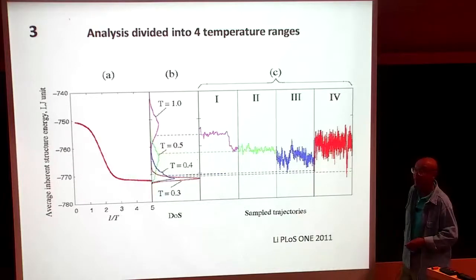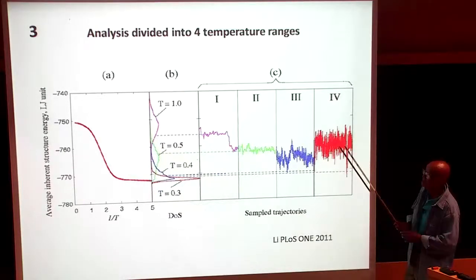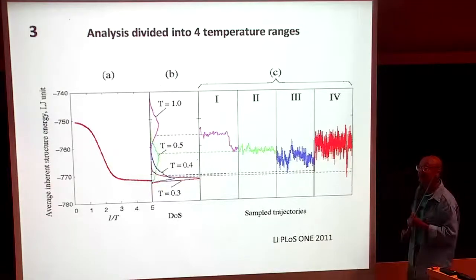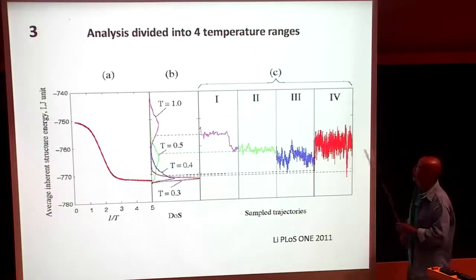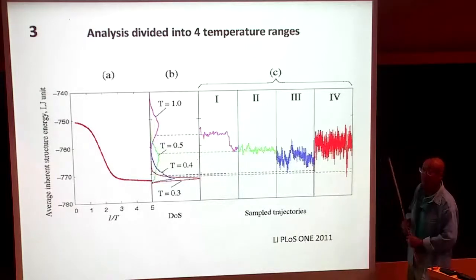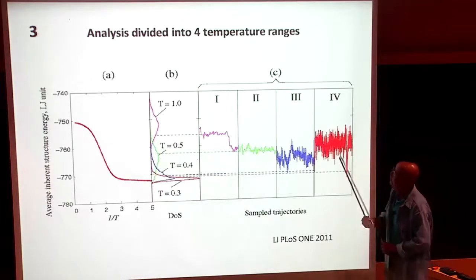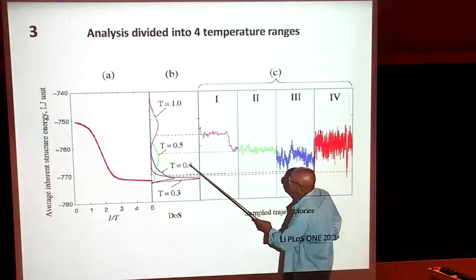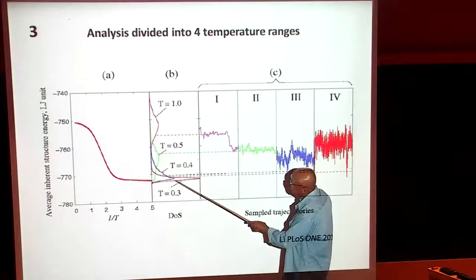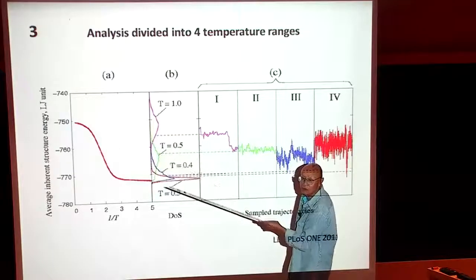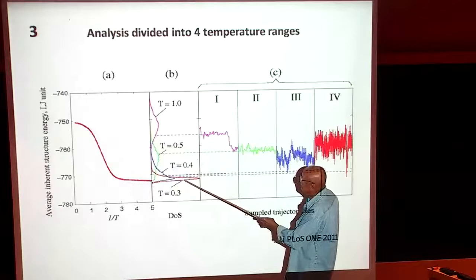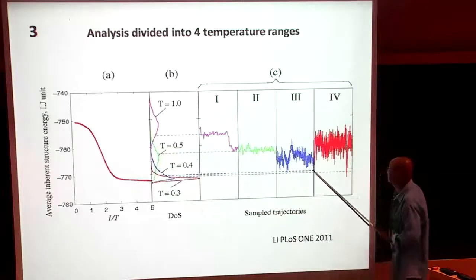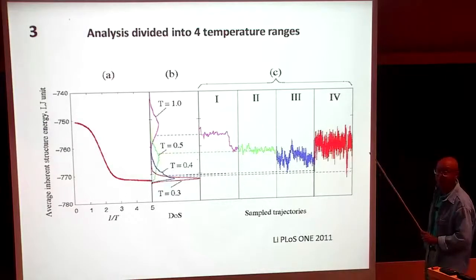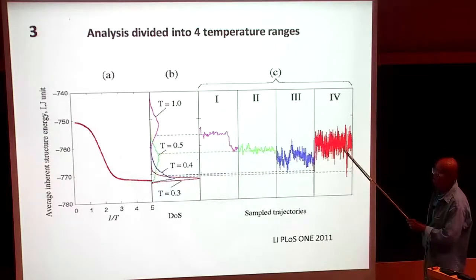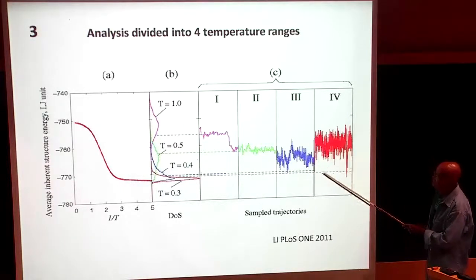So what is being plotted here? This is the transition state pathway at that temperature. Energy as a function of sample, right? But it seems inconsistent with the distribution of energies on the second column. You mean here? Yeah, the 0.3 is very, very narrow and has very low negative values, and I don't see those negative values over on panel 4. So this is not the same. Not the distribution of energy sample there, but the distribution that you show on panel B.